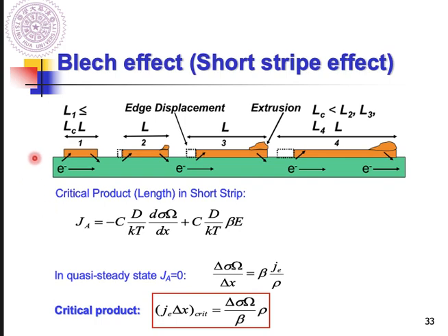Based on this slide, we're going to show you how to estimate. Here we have green metal 1 and deposited metal 2 in orange. You can observe that when the length of the interconnect gets longer and longer, the void formation and the extrusion get worse and worse. So when it's shorter than the critical length LC, we don't have a chance to observe the EM damage. So this is important, right? So how to calculate or estimate this LC?